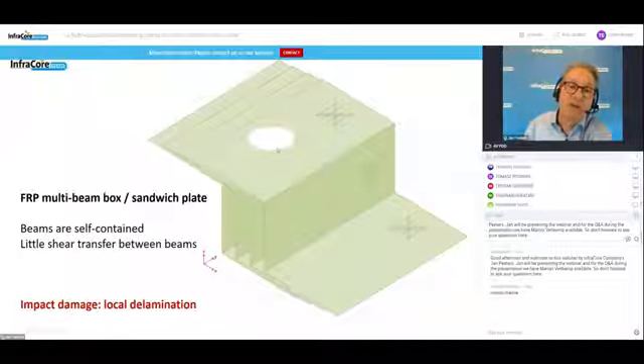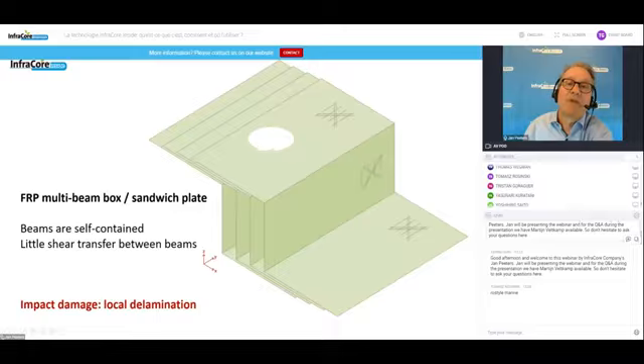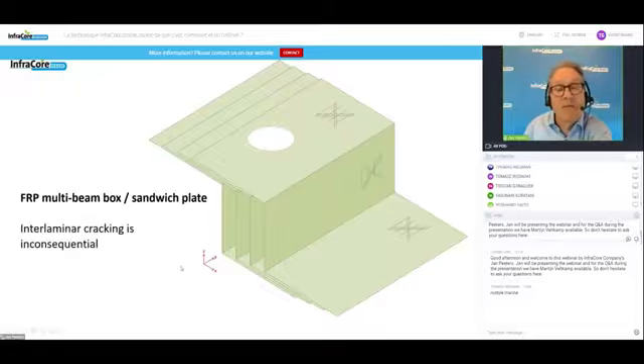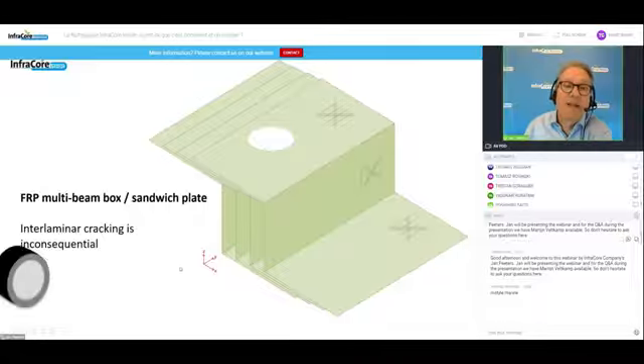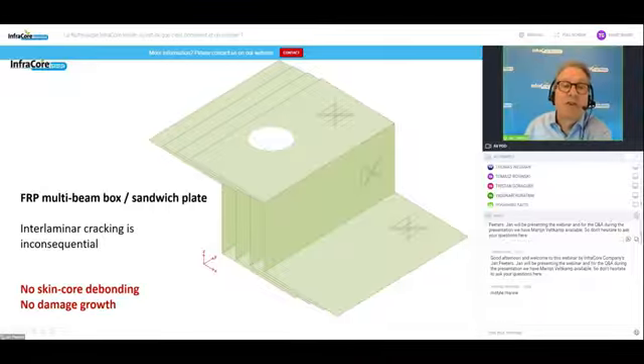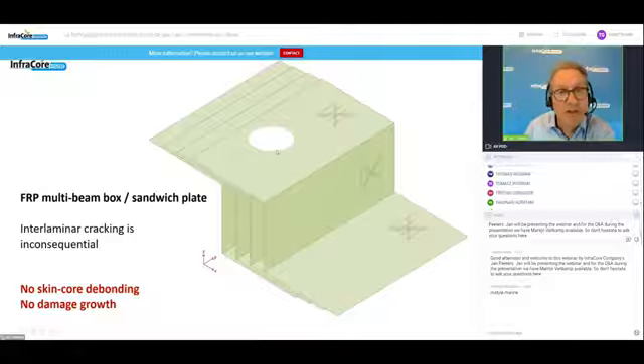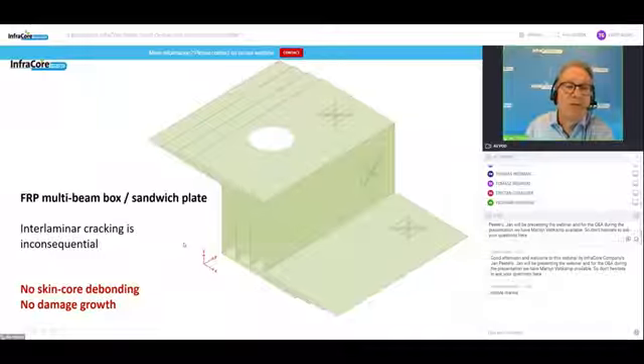We can also get in the delamination. But this delamination is only a local debonding between two beams which are essentially independent from one another. So it's a local phenomenon. And if you then start running wheels over it, what you will see is that because those two beams next to each other do not exchange much shear load, delamination between them stays stable. It doesn't grow. And that is the essence of what we do.